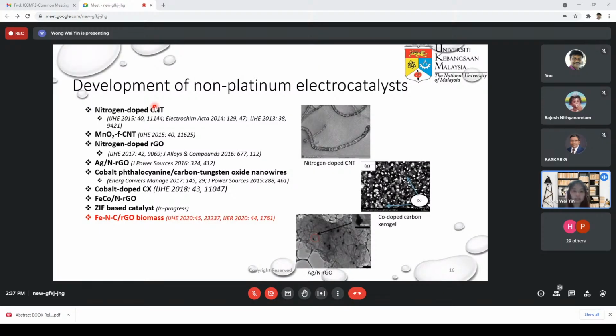And why carbon nanostructure? Conventionally we use carbon black or Vulcan carbon, which are amorphous in nature, and during long-term operation, carbon corrosion issues occur. With an amorphous structure, it's easier to be corroded, to be dissolved. But if we use a carbon nanostructure, the graphitic degree is higher, so it can reduce the tendency of this carbon dissolution issue. Hence, the attempts that we made earlier were on the carbon nanotube, and later on when graphene was in hot pursuit, we changed to the use of graphene, or in another form, reduced graphene oxide. Okay, so in the next slide, what I'm going to discuss is actually on this particular work.